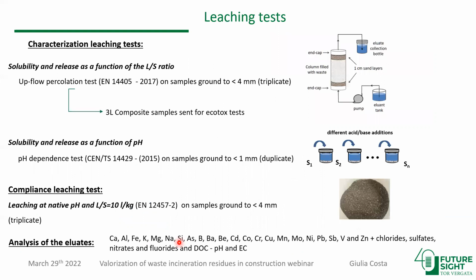Looking at these, as I said, we're performing both characterization ones. So the first one is the upflow percolation test that investigates release as a function of a liquid to solid ratio, whereas the second type of test is pH dependence test, where different individual batch tests are performed, adding different amounts of acids or base to obtain a specific pH value of the eluate. And then the eluate is analyzed.